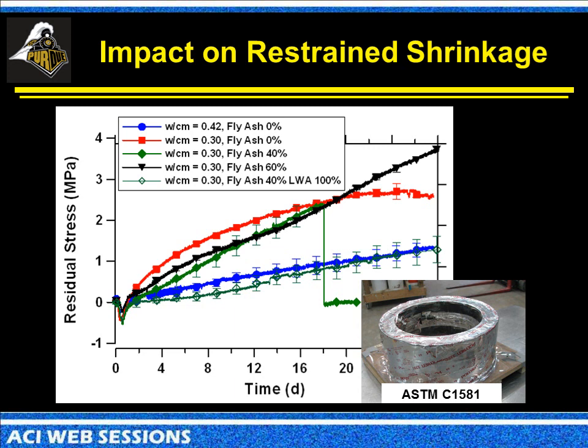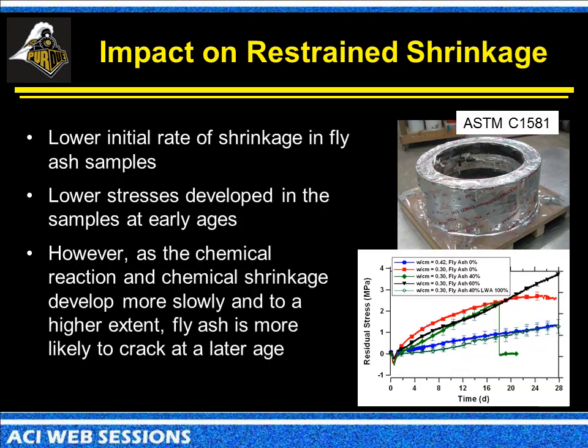So if we can supply that internal curing water, we can reduce the amount of self-desiccation, reduce the amount of internal drying that's taking place in the system, and keep the overall stresses low in the system. So in addition to hydrating more of the cement, we're going to get higher strengths in those systems, we're going to get reduced porosities in those systems, and we're going to build in less stress into the overall system.